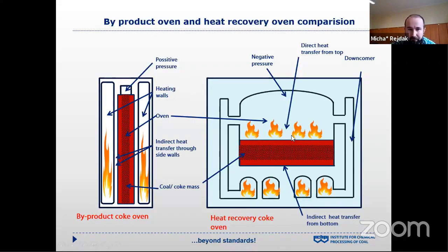For heat recovery ovens, on the right side, we have a hybrid heat transfer case. The raw coke oven gas released from the coal blend, which is located in the coke oven chamber, is burned directly above the coal charge with, of course, an insufficient amount of air. Air enters the chamber through the holes in the chamber door. The hydraulic system of the battery operates under negative pressure, which allows it to suck in the air and eliminate emissions from the oven. The partially burned gas goes through downcomers to the bottom flues.